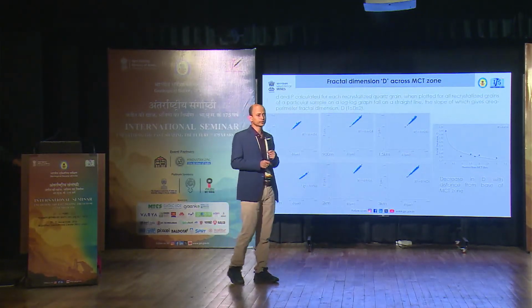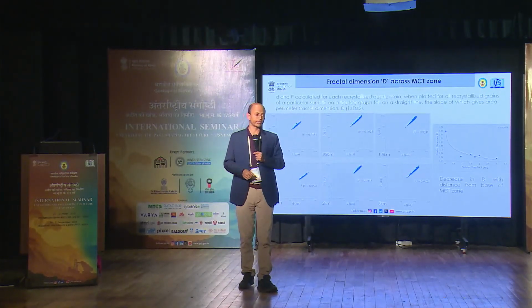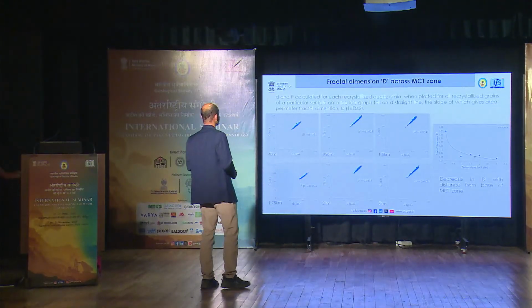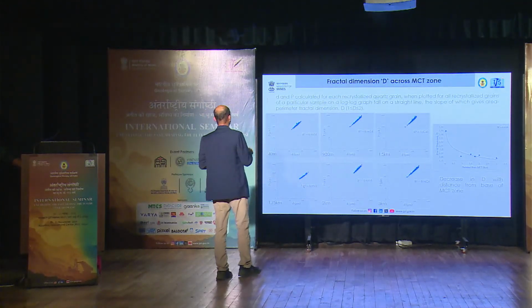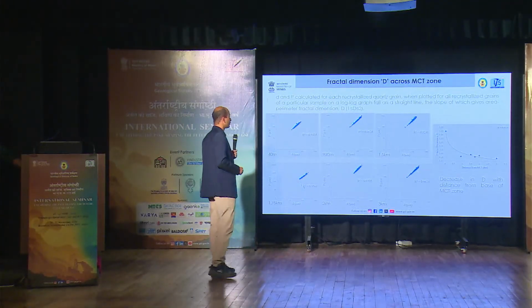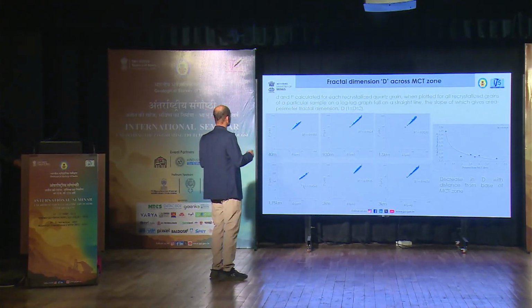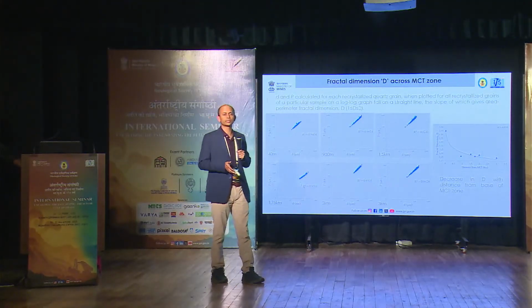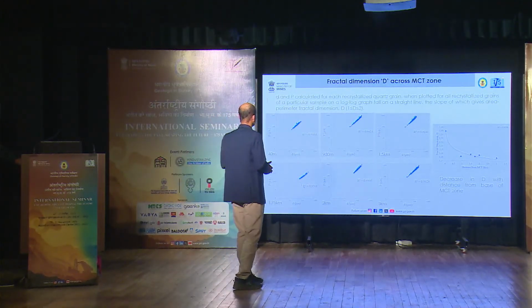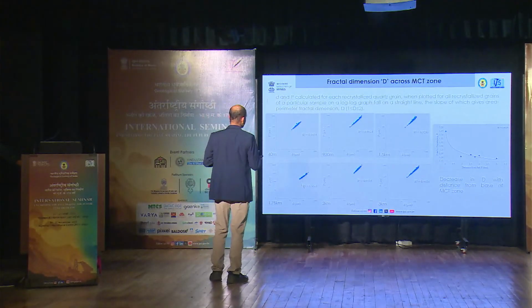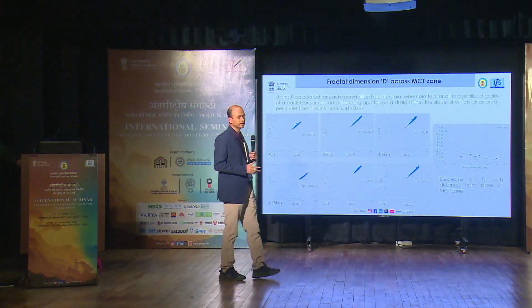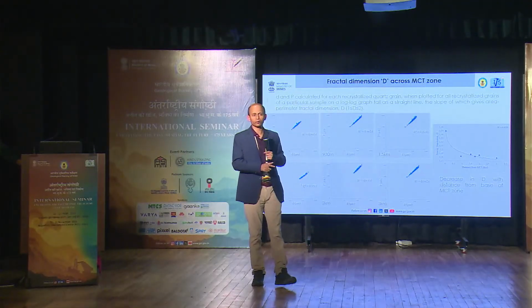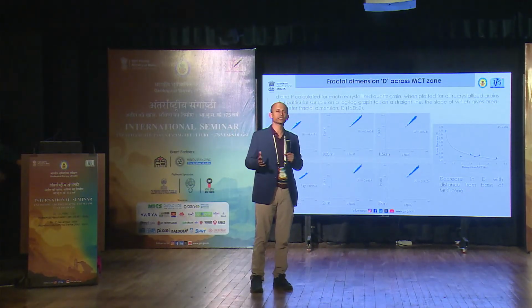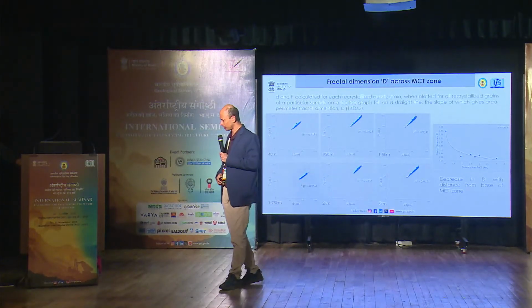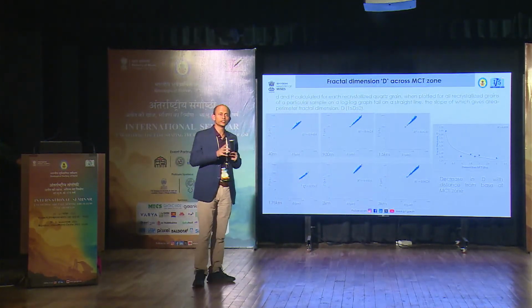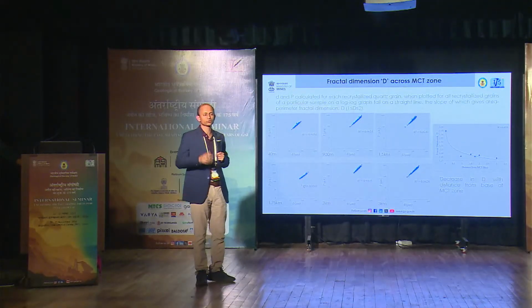So with the calculations that we did for the diameter, the grain size of the recrystallized quartz grains, and the perimeter, when we plot it in a log-log graph, they all fall in a straight line. The slope gives us the area perimeter fractal dimension. Now, this we have taken from Takahashi et al. 1998, but Takahashi et al. also borrowed it from Mandelbrot, who had given this equation quite 50 years back when he used it to predict the irregular shapes of the clouds.